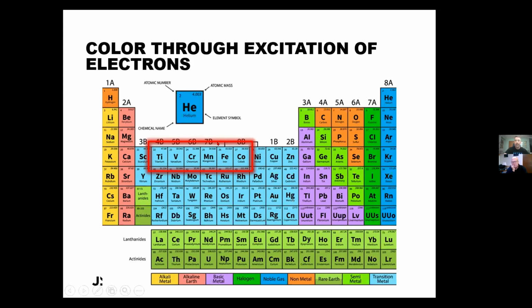making up for more than 90% of the color causes that we know, because they have the so-called d orbitals, and in these d orbitals there are some electrons which are not paired and therefore can be rather easily excited within the energy that we see in our visible light. So titanium, vanadium, chromium, this is mostly the material that you need, and some iron is also important for our